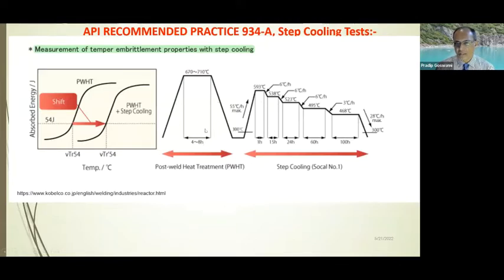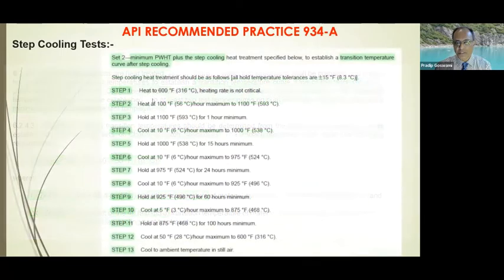What you can see here is that immediately after fabrication, the steels, the vessels or the intended welds are post-weld heat treated at this specific temperature, then cooled down to ambient temperature, typically room temperature. After that, whatever NDT and other requirements have to be fulfilled. Following that, they are taken to the step cooling temperature and exposed to this kind of heat treatment cycle. Of course, this is not done on the main equipment. This is done during the procedure qualification for welding. These are typically the step cooling test and step cooling heat treatment.